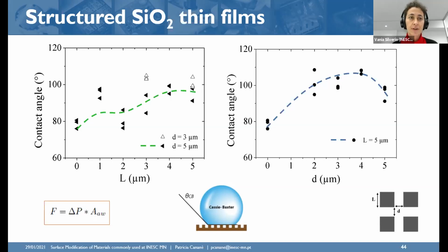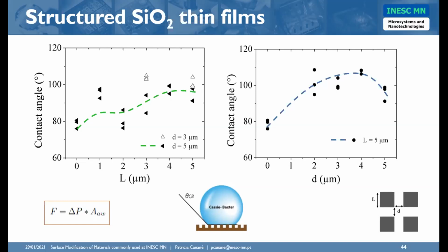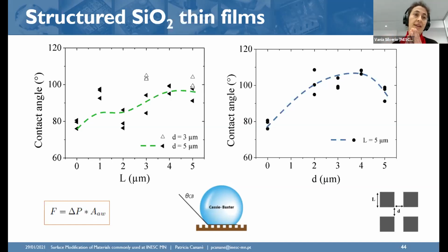For example, for structures where you need to do molds from SU8 into PDMS, if you have high structures and they are thin, an intermediate step of surface modification is very important, so you can actually peel your PDMS from the SU8. For example, in cilia, if you don't do any process to make this peeling easier, you lose a lot of cilia that remain inside the SU8.